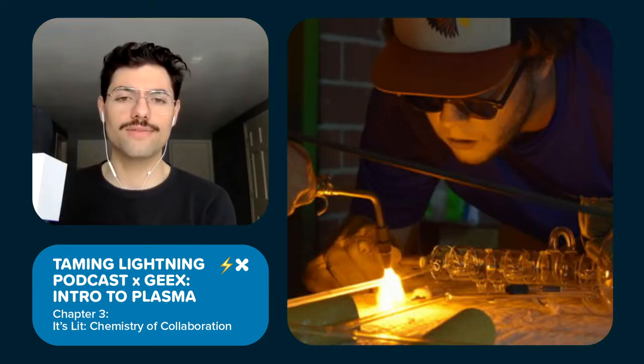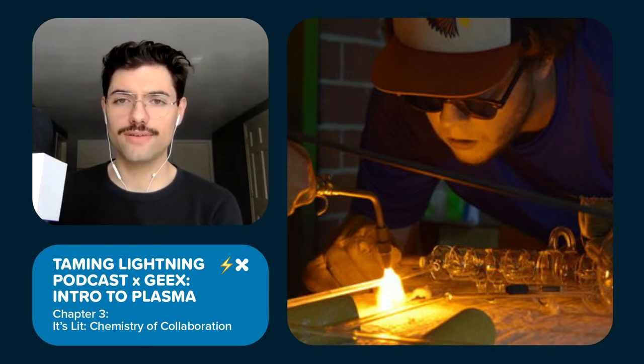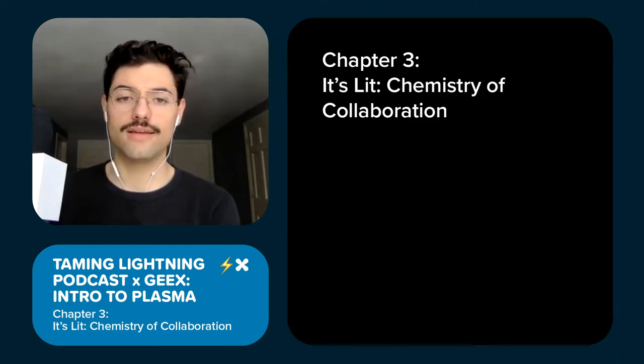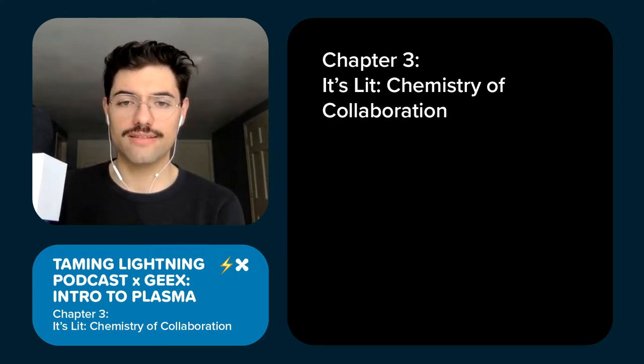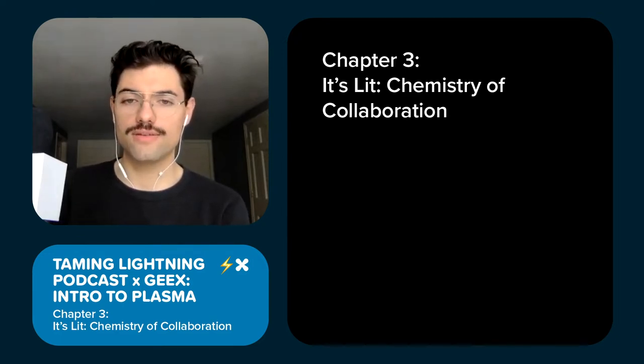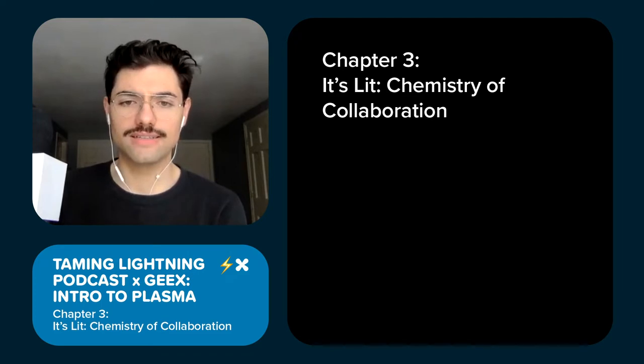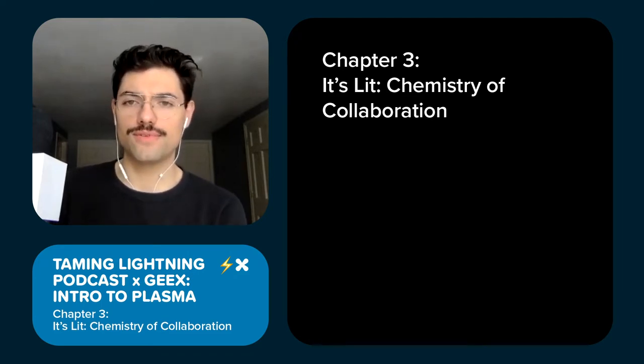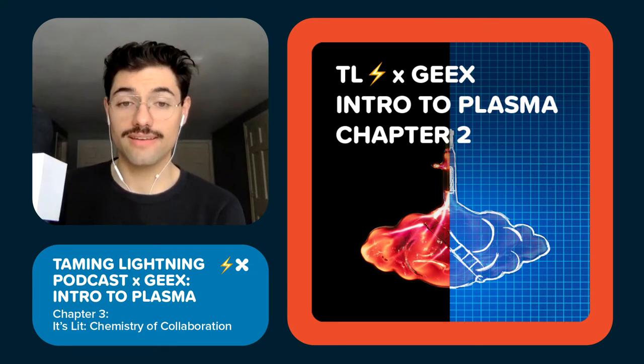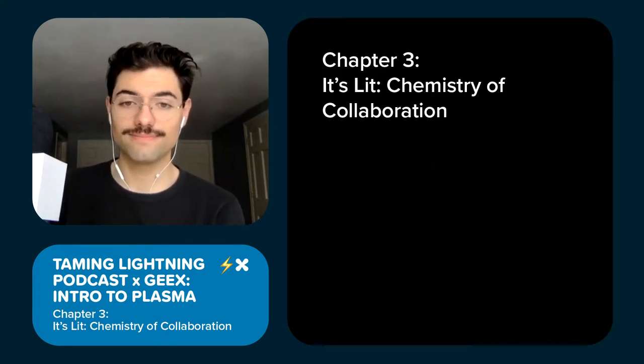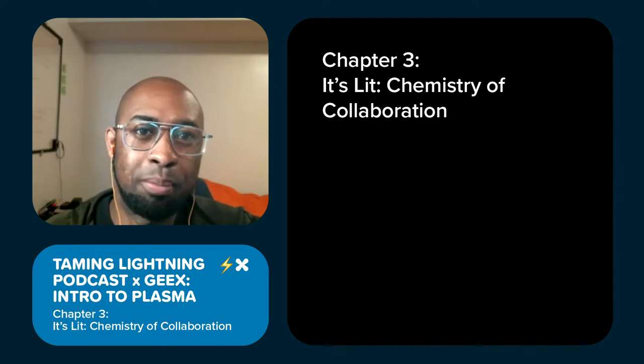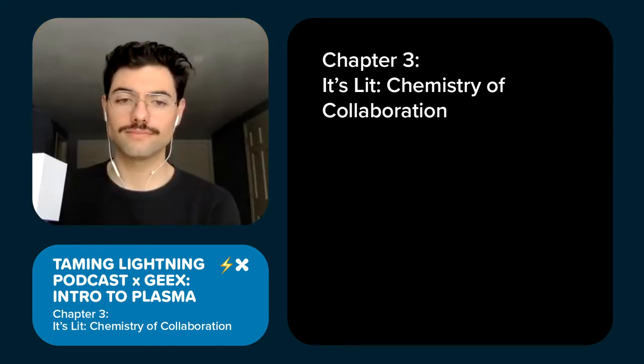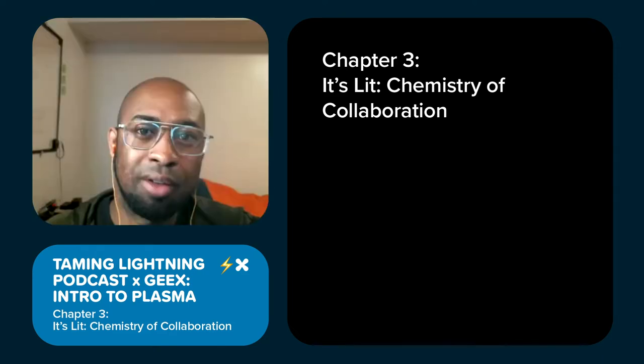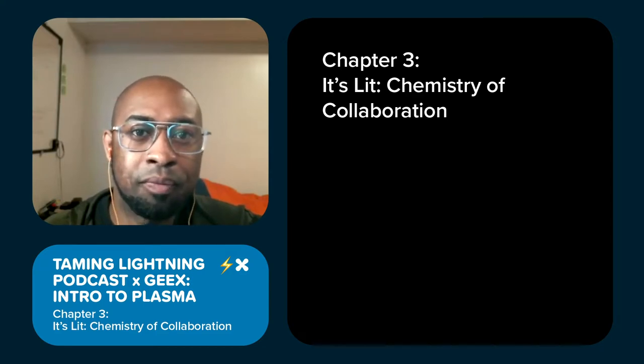And another way is welding your vessel directly to the manifold using the tubulated glass. We're typically working with 5 to 7 millimeter diameter glass, whether that be in borosilicate or soft glass. But do note that welding the tubulation happens at a smaller scale. Refer back to electrode welding in Chapter 2 for a general review of the welding process. And make sure that the vessel is attached to the system with no pushing, tugging, or any movement of the components. And also make sure that the piece is not on a conductive surface.